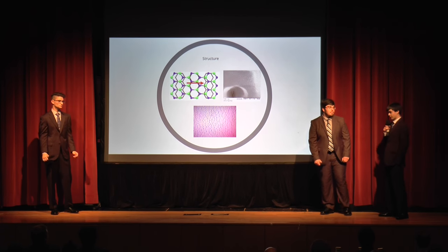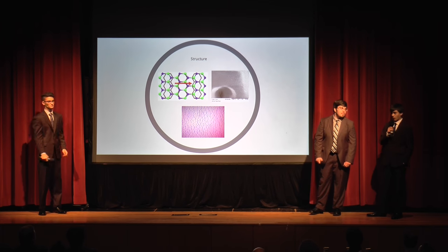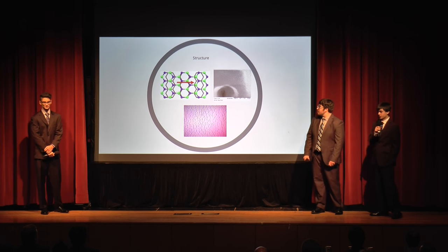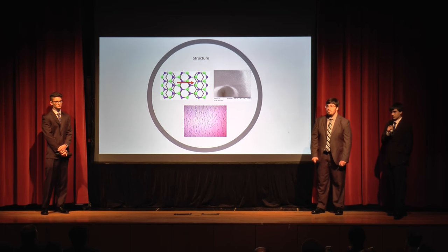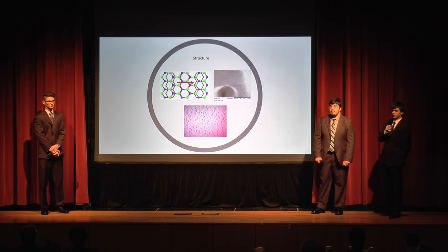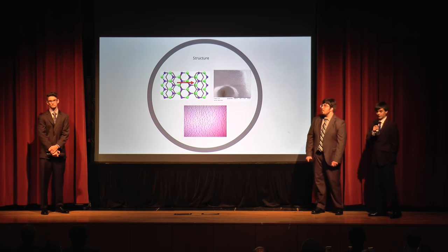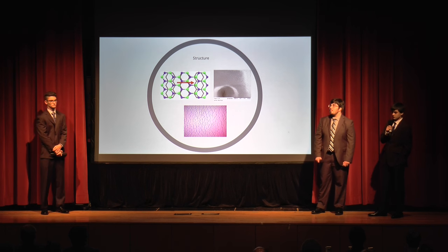After we annealed, we found a common structure throughout all of our films, and that was a honeycomb structure. And we believe this honeycomb structure will allow an electrical current to flow through with less resistance than a non-annealed thin film.